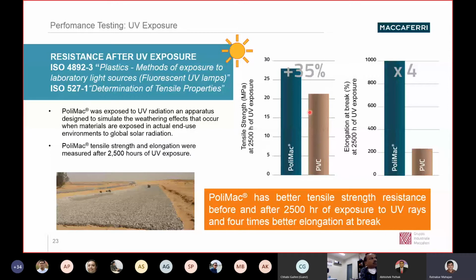When you talk of a cold condition, all along the Himalayas, let's say if I have to start from completely northeast to the north part of the country up to Jammu and Kashmir, and even if you go towards Nepal or Bhutan, that area can be easily covered with this product. And Polymac retains its properties, I would say with better tensile strength, even after 2500 hours of UV exposure. So it has better elongation at break compared to PVC, roughly 4 times higher. So it still remains an elongating product, not a brittle product.